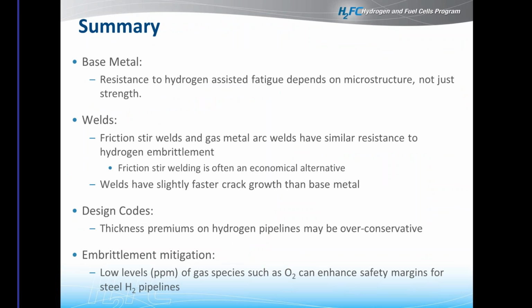That seems to be more of a dominating effect. We looked at two different welds, a friction stir weld as well as a gas metal arc weld, and they actually showed fairly similar resistance, which potentially has some benefits in terms of cost savings from the friction stir weld standpoint. Overall, the welds had a slightly higher fatigue crack growth rate than the base metal.